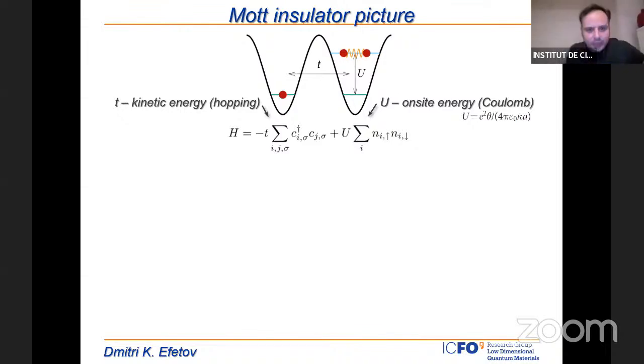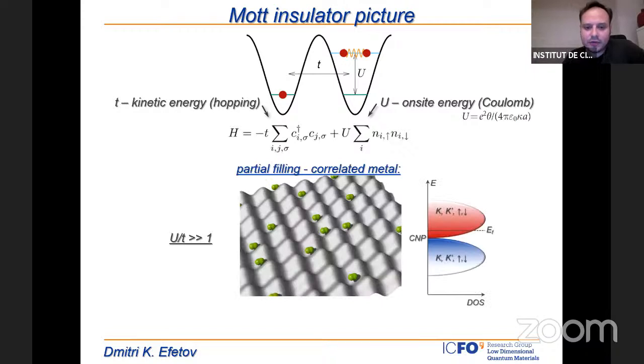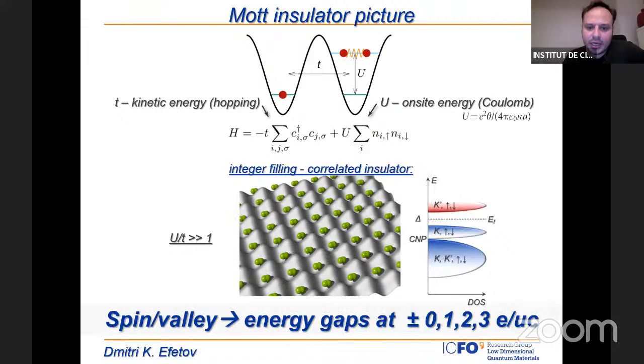Basically, we think of individual atoms per moiré unit cell. What we need to account for is that one electron can hop between different lattice sites, and the hopping term, or kinetic energy, is t. As I mentioned, t is very low in twisted bilayer graphene, so t can be neglected. The other important parameter is U. This is the energy cost if you have two particles per lattice site, basically the Coulomb energy between the two particles. What happens is that if our bands are partially filled, then electrons can just hop between lattice sites. But whenever we get to the condition that we have integer fillings of electrons per unit cell, again, integer fillings here can be 1, 2, or 3 because of the four-fold degeneracy.